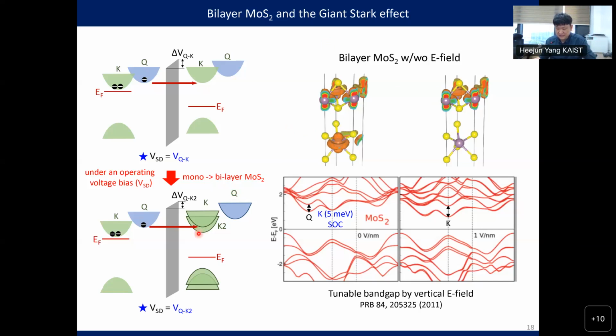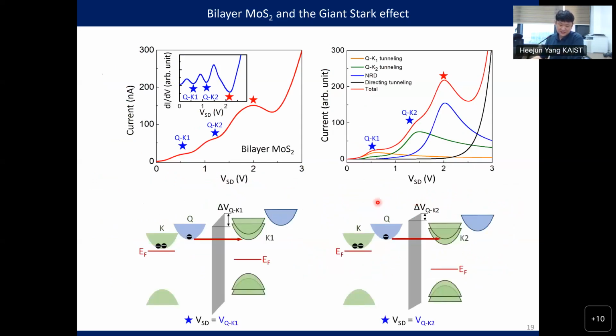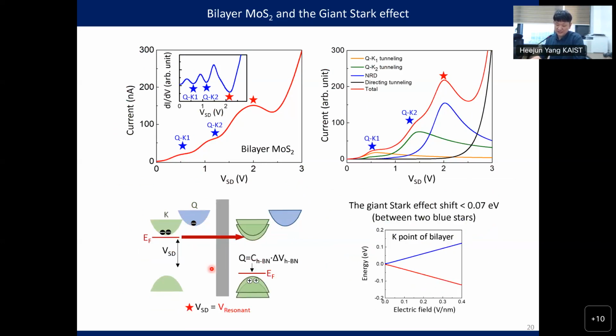And this is what we see in DFT, first-principles calculation. We have bonding and anti-bonding features at the Q point. And here, Q point, K point, if we apply some electric field, the bilayer MoS2 splits its bands. So what happens in the bilayer resonant tunneling device? Here we have two peaks. Actually, these two peaks are coming from tunneling between the Q valley and K valley. Of course, their momentums are not exactly the same, so they cannot make a peak. They can make only a shoulder feature. And then here we have a more blunt peak. It's because here we have K point energy matching, but momentums cannot be perfectly matching. So we have a more blunt feature here. So we can have these two shoulders from these two split bands between the Q valley and K valley.